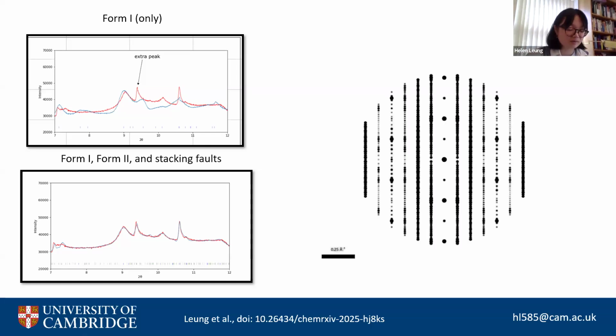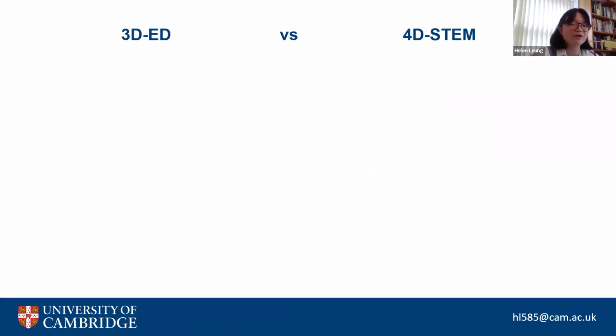And what's really neat is we also simulated the electron diffraction data just very simply kinematically with our new supercell model. And you can now see the origin of this streaking that I was talking about in the diffraction pattern. And crucially, you can see that the center reflections that correspond to the distances between the hydrogen bonded stacked planes, those reflections are not streaked. And we wouldn't expect them to streak because we think that those remain invariant in their position. Okay, so to wrap up,